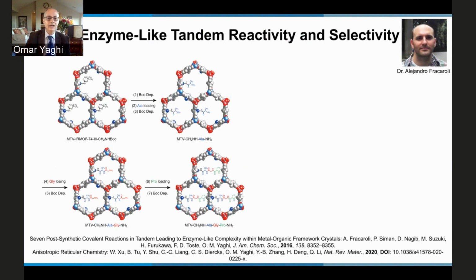Okay, and one thing to keep in mind, and some of you may feel very uncomfortable with this, is that when you run a reaction inside a MOF, unlike molecular chemistry, if your reaction is not 100% complete, then you have the converted functionality as well as the unconverted functionality or the partially converted functionality. They're all encompassed within the pores. So the pores at the end, when you're doing, as in this case, 7 different transformations, protection, deprotection, since these reactions are not 100.000% complete, then you have what I call a multivariable environment, meaning that you not only have these short peptides made from 4 amino acids, but you also have the shorter versions and the incompletely converted functionality.